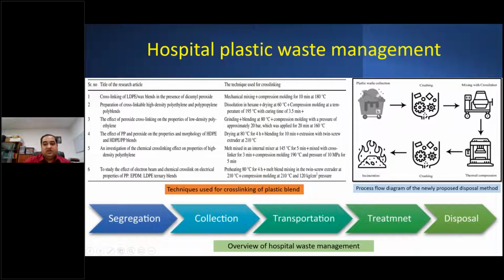and a process flow diagram that we suggested, in which we collect the plastic waste from the hospital, crush it down, mix it with the cross-linker, thermally compress it, and then finally we move it into a crusher again and through the incineration. In this way, if anybody wants to collect this plastic, they won't be able to reuse it, because the cross-linking would discourage the thermal processing.